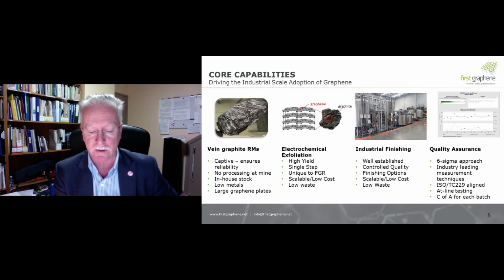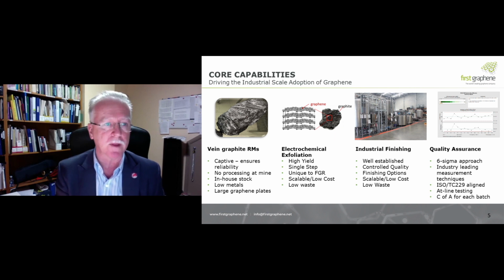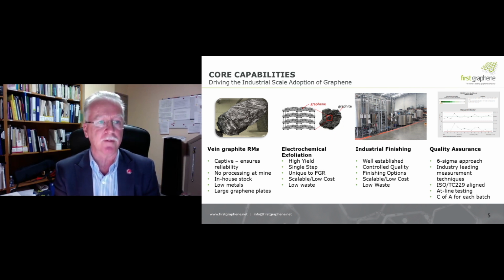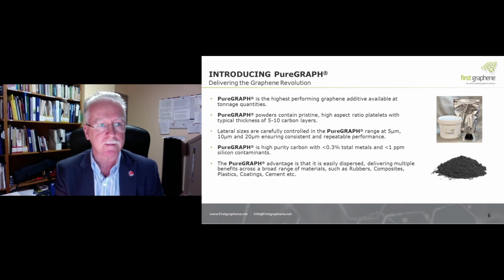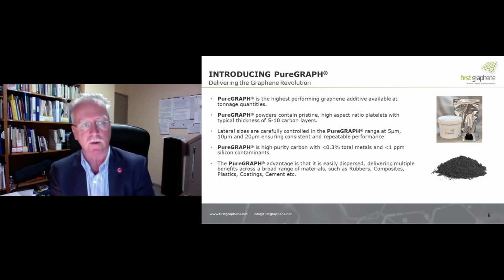Our electrochemical exfoliation process involves using dilute sulfuric acid and electricity to dissolve the lump graphite in an electrowinning cell. If you have a look at that diagram there, what effectively happens, the layers of graphene peel off like cards on a deck of cards, and we come up with jumbo size platelets with a diameter of about 70 microns. We then have a series of finishing steps that tailor the size of the platelets to suit the customers. The PureGraph range of products can be 5, 10 or 20 microns in diameter, with aspect ratios of 2,000 to 2,500, which is much better than the standard 500 to 700 ratios that most other producers who use synthetic graphite end up with. We usually deliver PureGraph in the powdered form, but we can also deliver an aqueous product.